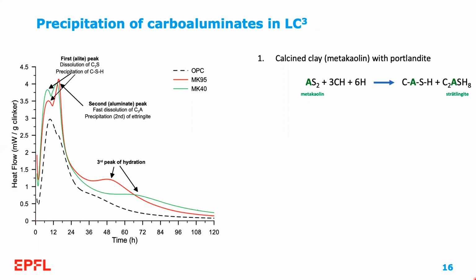Let's move now to precipitation of carboaluminates in LC3 and why this enhanced formation of carboaluminate is so special and makes LC3 such a special blended cement for our sustainable concrete endeavor. So summarizing what we know now, we have three main peaks that we can clearly identify during LC3 early hydration. A first alite peak associated with dissolution of C3S, leading to precipitation of CSH. A second aluminate peak associated with the fast dissolution of C3A, leading to the second precipitation of ettringite, as we discussed in the previous slide.